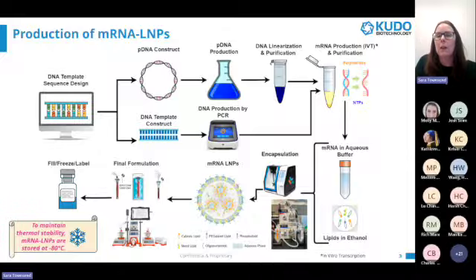For the production process, the lipids will be dissolved in ethanol, and the mRNA will be diluted in an acidic buffer. These two solutions are then separately loaded onto a syringe pump microfluidic system or an HPLC T-mix device. The two liquid streams will converge in a narrow channel, and the rapid mixing will cause the lipids and mRNA to self-assemble into this beautiful particle here.